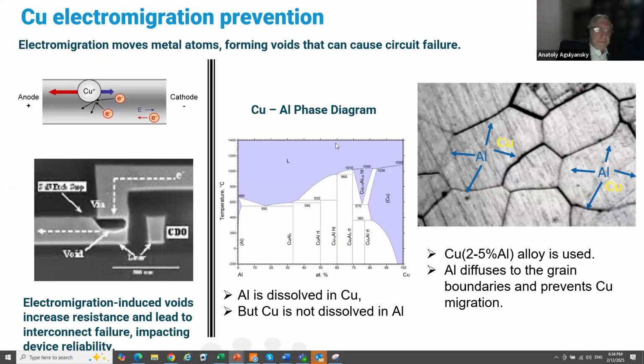Electromigration is a very, very interesting phenomenon where a cloud of electrons moves and picks up ions in the metal and actually moves metal from one place to another, which could result in the formation of voids within the metal interconnection. And this void is terrible. This is a failure of the device. Also here we found a solution.